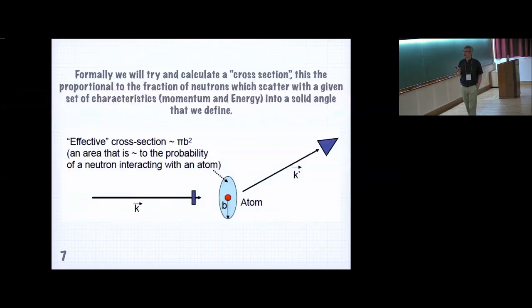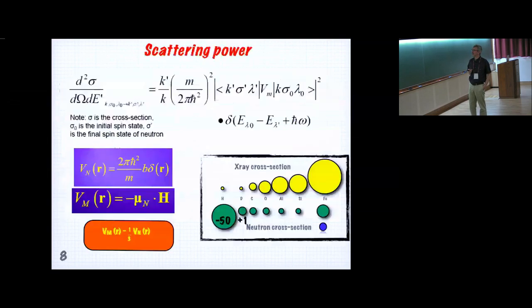But in general, what we are looking at, and I'll stop right here, is a well-defined incoming beam. Depending on the experiment, you know its momentum and you know its energy, or maybe you only know where it's going, its momentum. And you look at the scattering probability into a certain solid angle of another beam. If you need to know its energy, you work out its energy, and then the difference in energy here is an energy transfer. And by Bragg's law, you can get the momentum transfer or the Q, so the correlations. And you come up with some of those pretty pictures you've already seen of spin waves or spinons and so on from that.